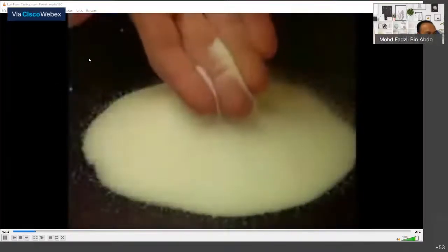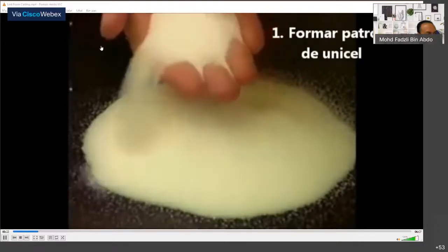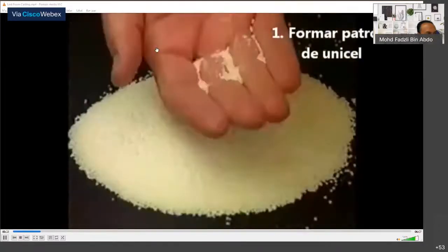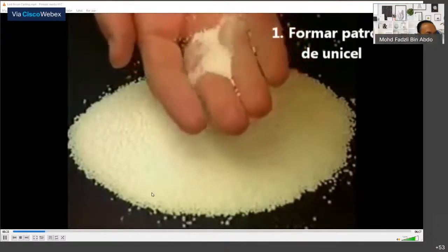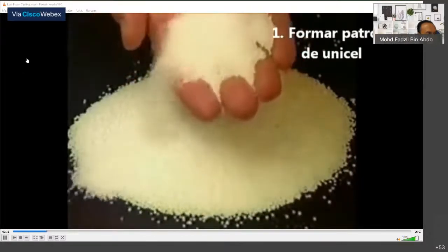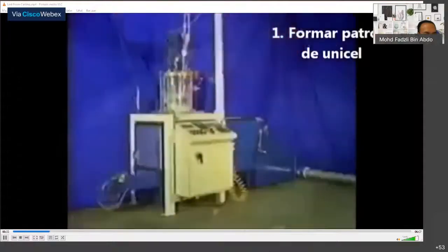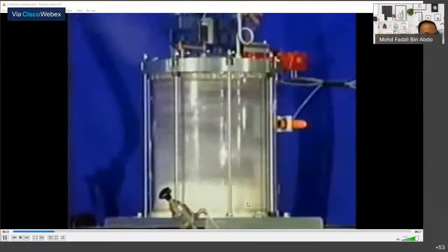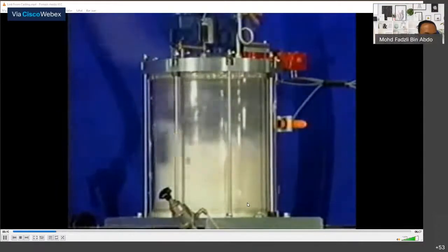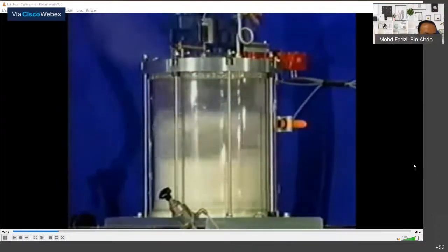The process begins with polymer beads, which must be expanded to a controlled low density for molding. The beads, as purchased, have a cellular structure and contain a gas or blowing agent, usually pentane. In a pre-expander, steam is used to heat the beads, softening the polymer and expanding the gas. Control of density and bead distribution is critical in this operation.